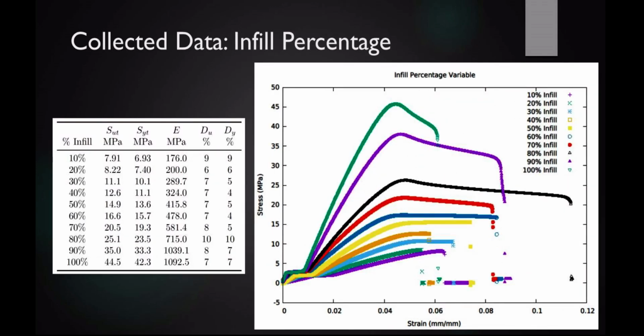Next we have the infill percentage data, and this shows an exponential increase as we increase the infill percentage. So really we have 3 main groups, at least the way that I see the data, and that I'll be going forward with my own 3D printing and testing. We have below 60%, which is really good for prototyping when you don't want to waste material and you just want to make sure that something works. Then you have 70 and 80%, which are okay, they work, but it's really probably smarter to stick to 90% actually.